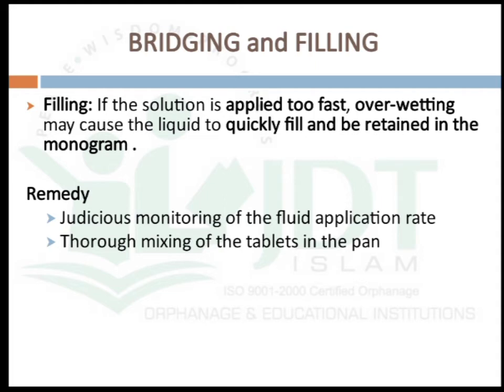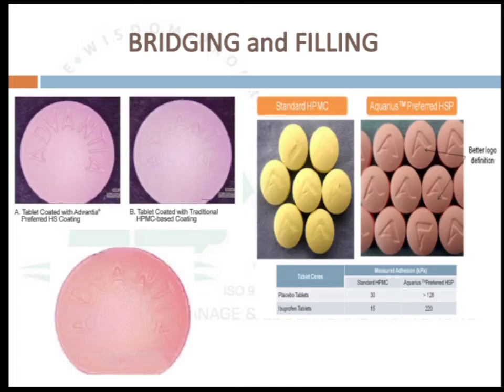Regarding filling: if solution is applied too fast, over-wetting may cause the liquid to pool, fill, and be retained in the monogram, making the monogram invisible. This can be rectified by careful monitoring of the fluid application rate and through proper mixing of tablets in the pan. This is a picture showing bridging and filling — the monogram cannot be seen due to filling.